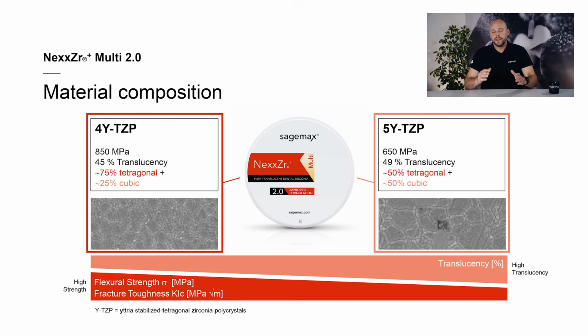Next, I will explain the material composition and disc structure of NextCR Plus Multi 2.0 in more detail. Like its predecessor, NextCR Plus Multi, NextCR Plus Multi 2.0 consists of two different zirconia materials. The medium translucent zirconia type 4 YTZP with an average flexural strength of 850 megapascals and an average translucency of 45%. And the high translucent zirconia type 5 YTZP with an average flexural strength of 650 megapascals and an average translucency of 49%.